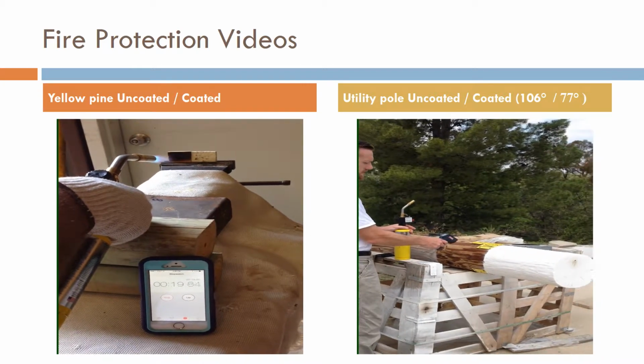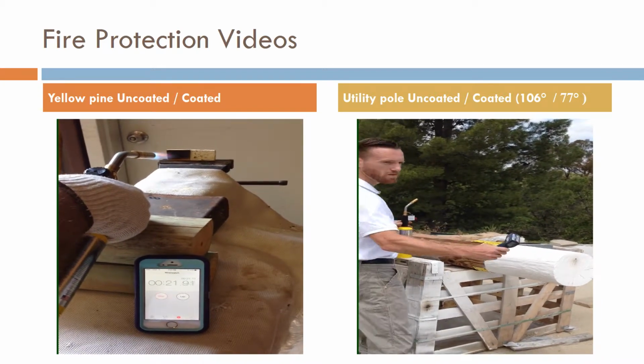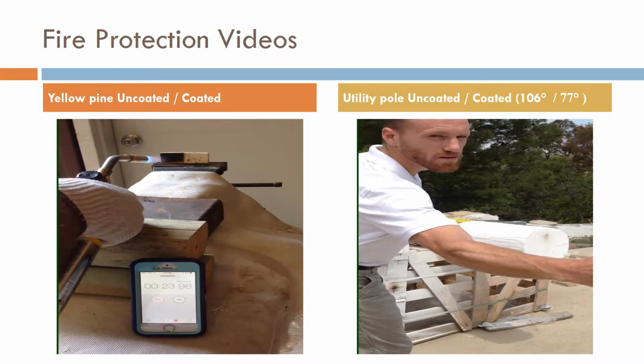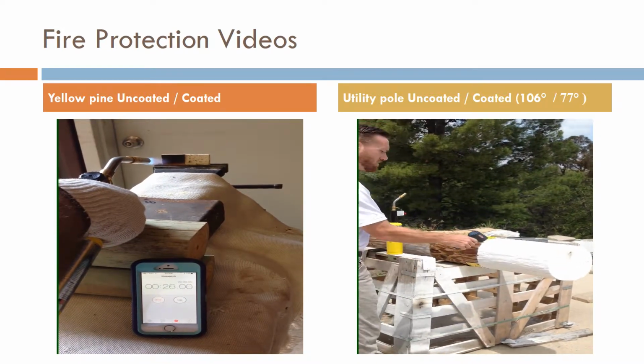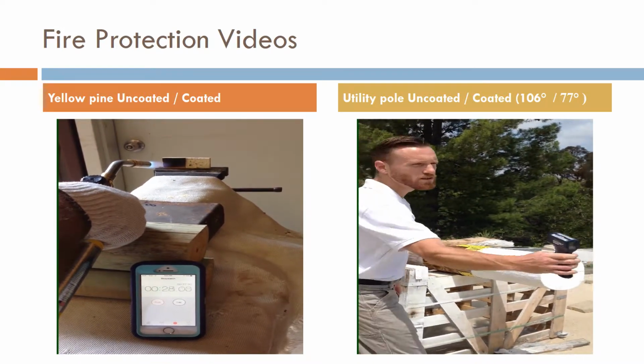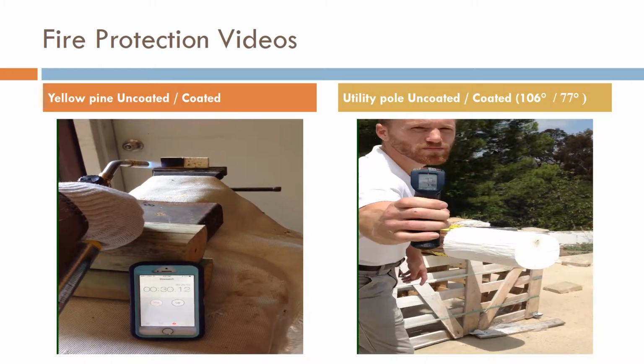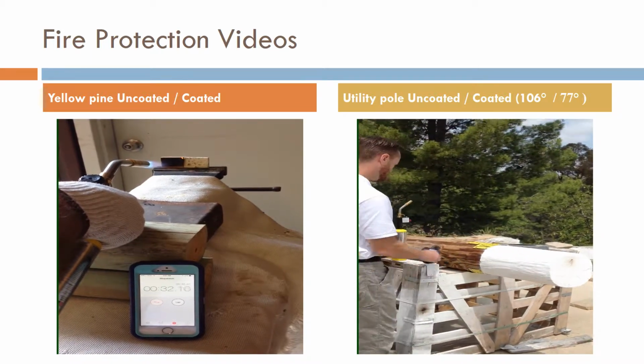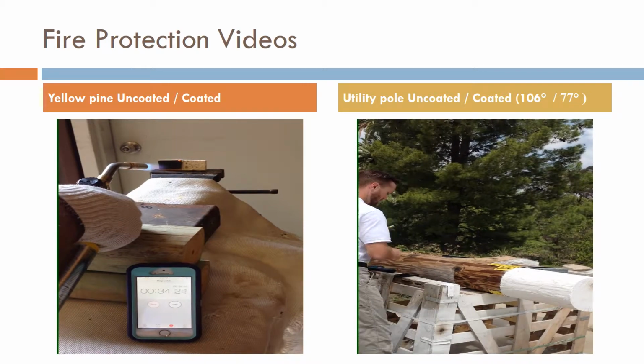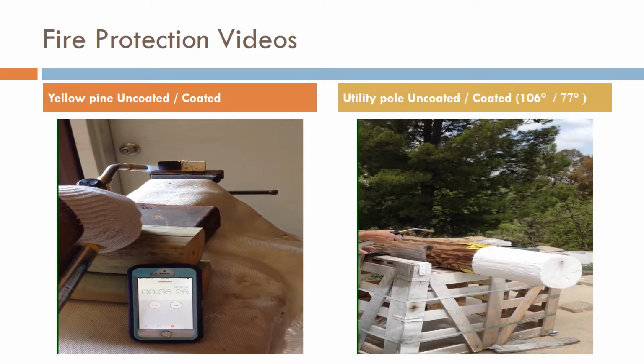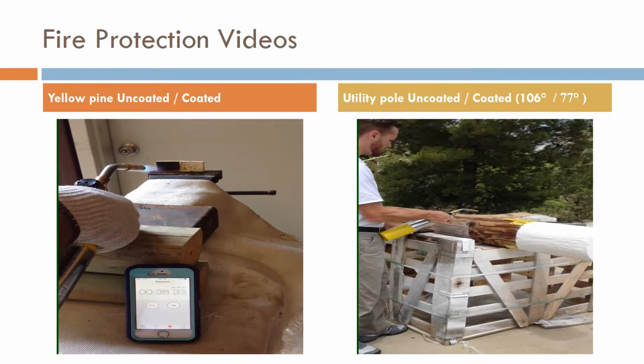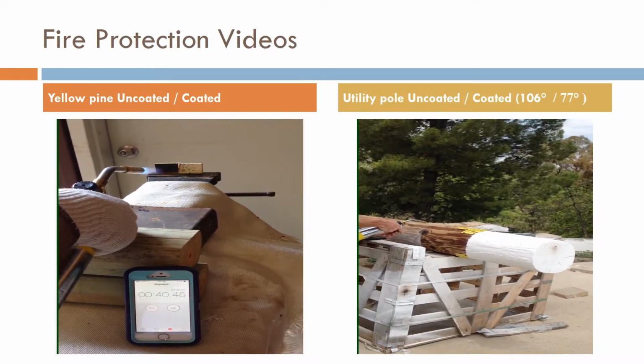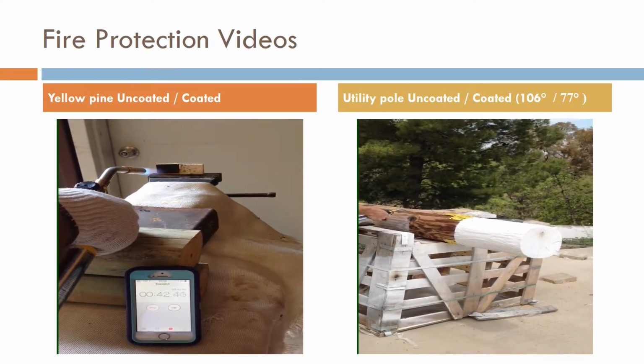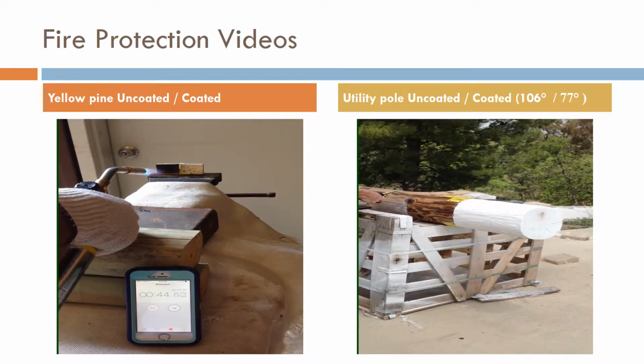In this video, a 1-minute burn test with a 3,000 degree MAP gas torch on a utility pole. A temperature reading of 106 versus 77 illustrates the coating's ability to both radiate and emit thermal heat. You will see the uncoated side immediately catches fire and continues to burn throughout the video. The treated side turns a slightly yellowish brown as it reacts to the heat and seals out the fire.